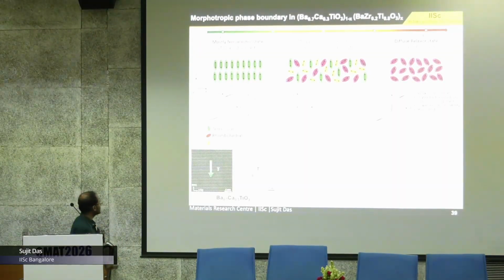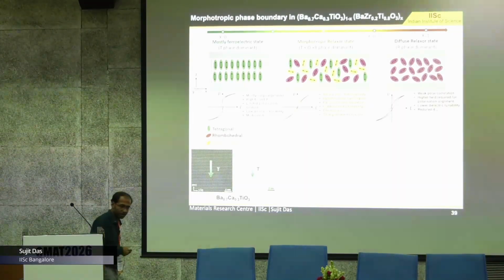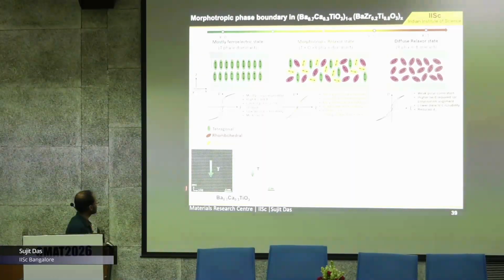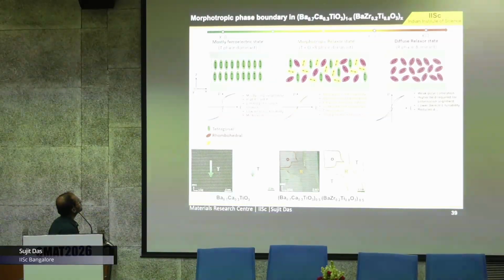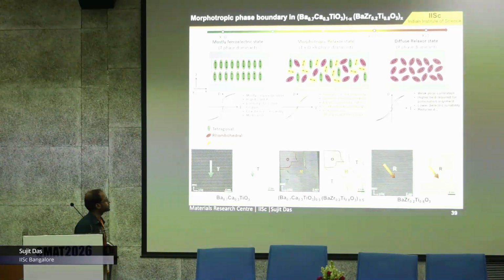We grew this material, and then we did the TEM image, cross-sectional TEM. For the first case, BCT, we are showing a tetragonal phase, and then we go to the 50-50, and we can see this mixture of tetragonal, rhombohedral and orthorhombic phases. And once we go to x equals 1, we can see rhombohedral phases. So we can make this kind of morphotropic phase boundary in these combinations.